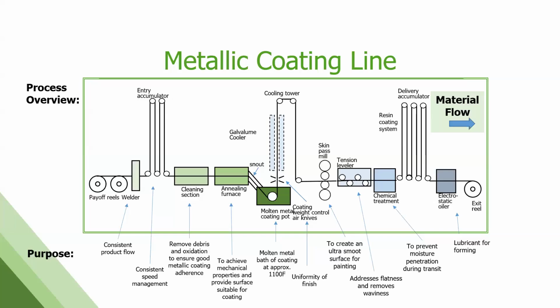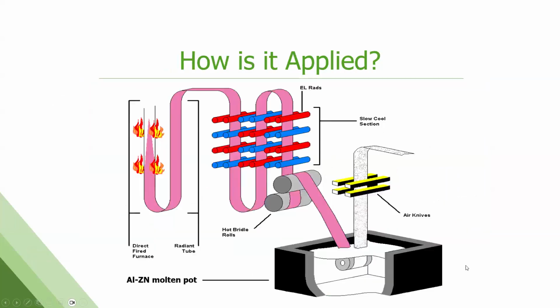We cool that strip down, and it goes through a skin pass mill. That kind of just makes a very nice smooth surface. At a microscopic level, if you were to look at this product, it looks like little hills and valleys until you skin pass it, get that nice and flat. Tension level it to get flat shape, and then wrap it up at the other end so it can go on to its next step. So there's a lot happening in these lines besides just the metallic coating portion that all have to work together at 400, 500 feet a minute.